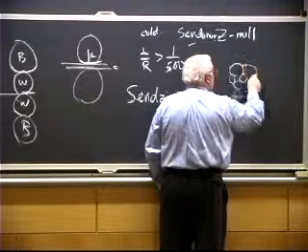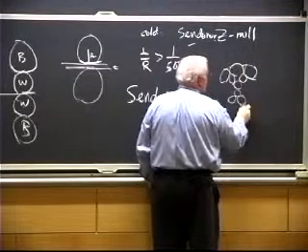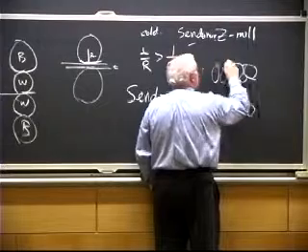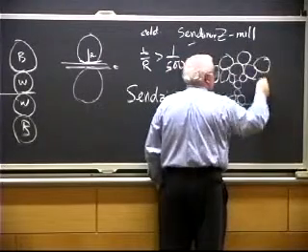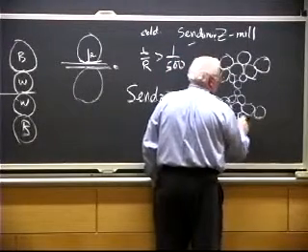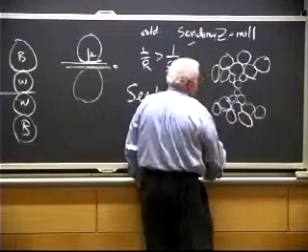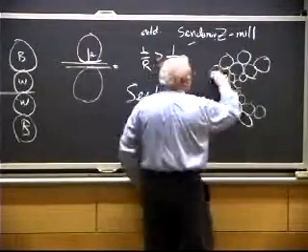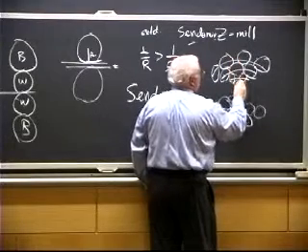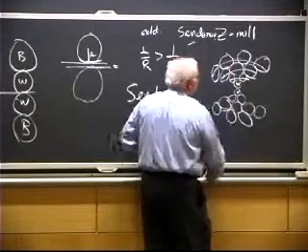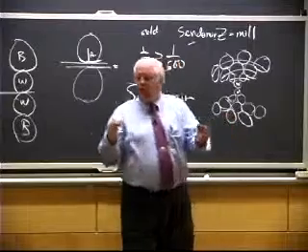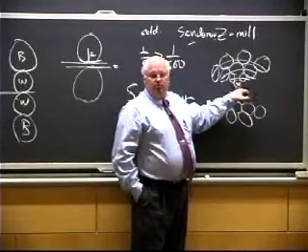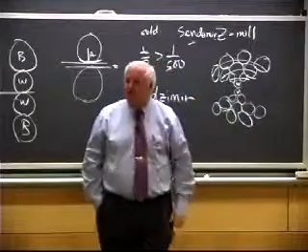And it actually has 4 levels of rolls that get larger and larger just to back up the work rolls. You end up with a ring of 4, a ring of 3, a ring of 2, and then your work roll in between. And all of this is just to back up that little bitty work roll. A typical Z mill might have 1/2 inch or 3/4 inch diameter work rolls. It's just a little thin piece of steel.